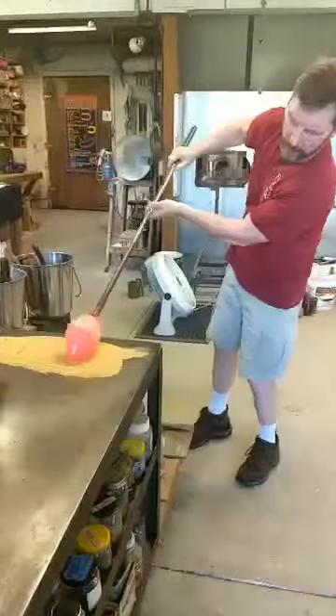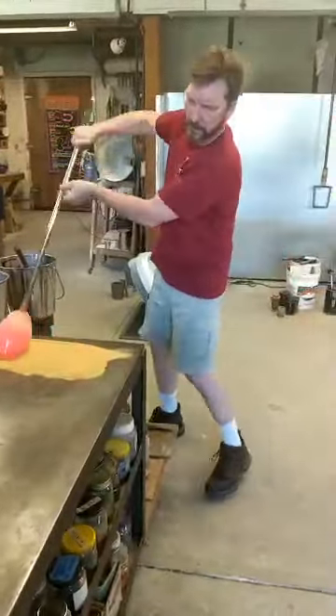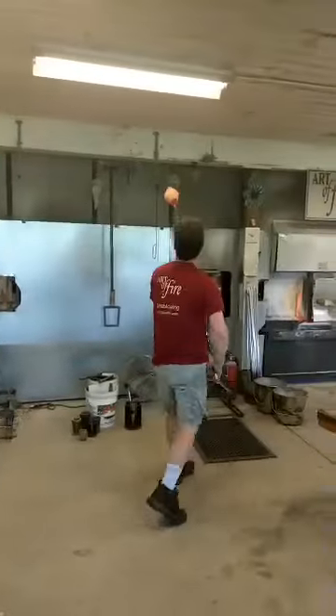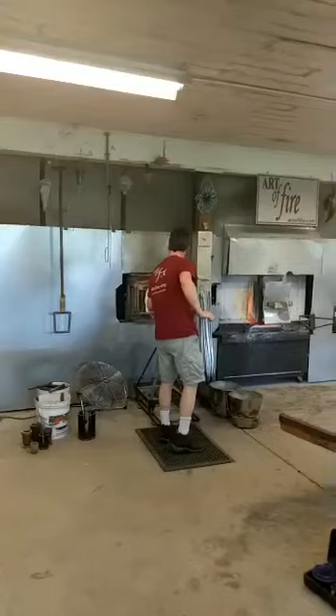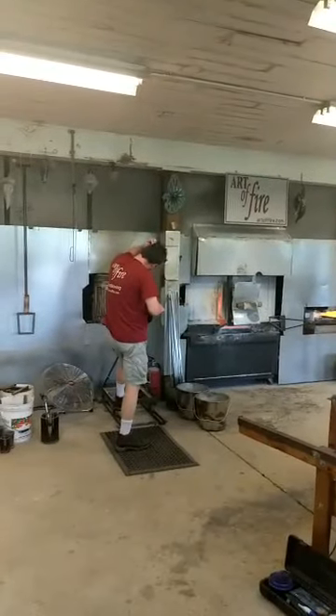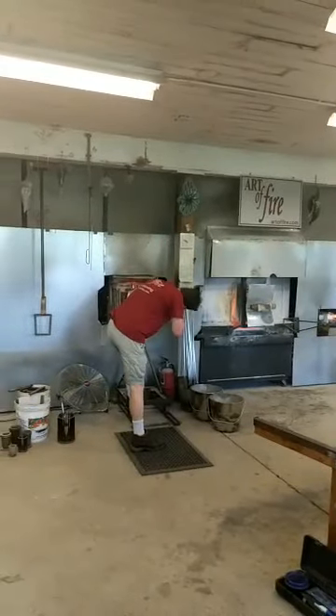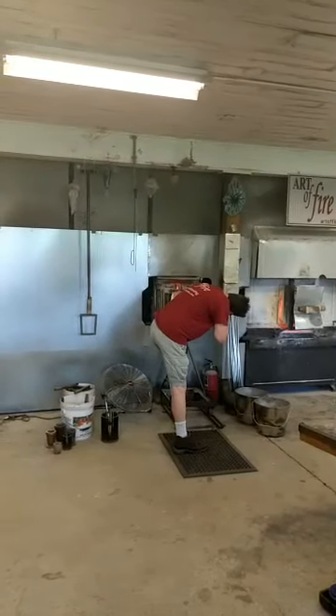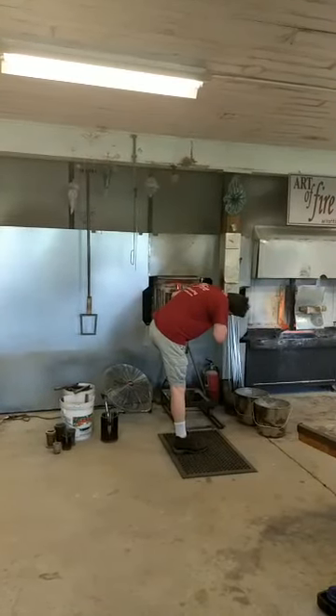And that melting process can take about 8 hours or so. And then after that period, it has to do what's called fining out. So the temperature is reduced and the bubbles come up, because there would be some created from the melting, and we go a little bit below our regular operating temperature and then bring it back up. And so that whole process basically takes overnight.